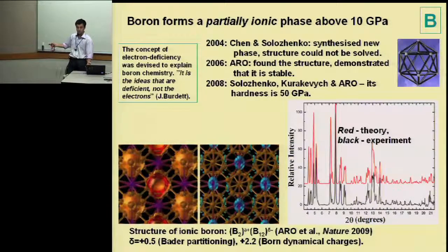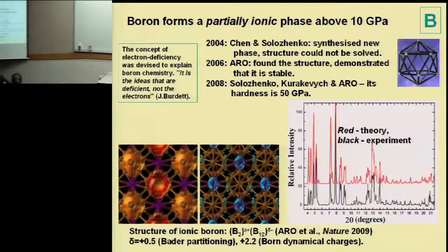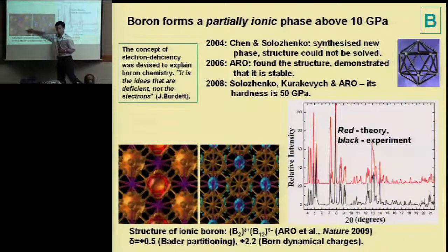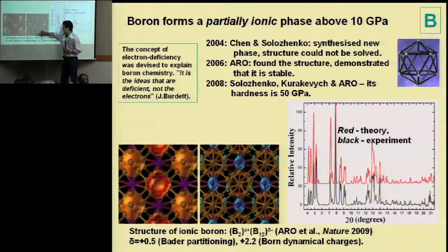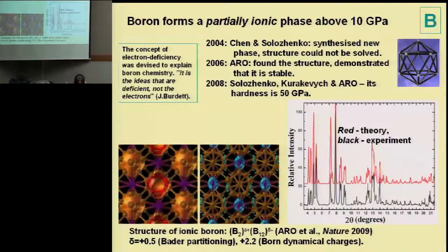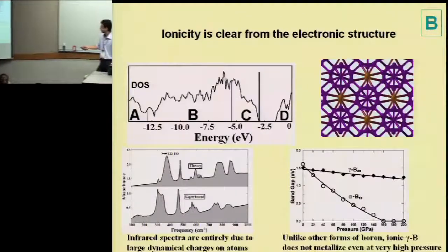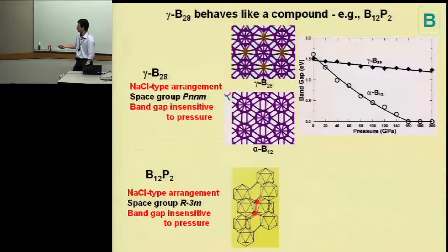It was found that this is a superhard material, one of the hardest known materials, about the fifth or sixth hardest. And it has a very peculiar structure where there is a strong charge separation between the boron-12 icosahedra, which attract all the low-energy electrons at the bottom of the valence band, and the boron-boron pairs, which concentrate the top of the valence band and the bottom of the conduction band. In other words, holes in the electronic distribution. Okay, I will not tell you more.